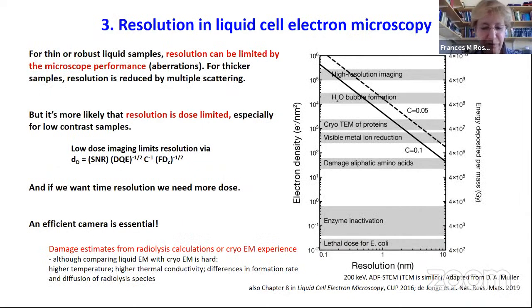effects. But so I've already referred to the fact that the microscope is going to be changing the sample as you do the imaging. And so that makes us think about what is it that really limits the resolution of the images in a liquid cell experiment. For very thin samples, or for samples where you don't care how many electrons you use to make the image, the resolution is then limited by the performance of the microscope. But it's much more typical that the resolution is dose limited. In other words, you cannot shine enough electrons on it to see your object over the noise, because the sample is too sensitive to the electron beam to be worth imaging after you've illuminated it with so many electrons.